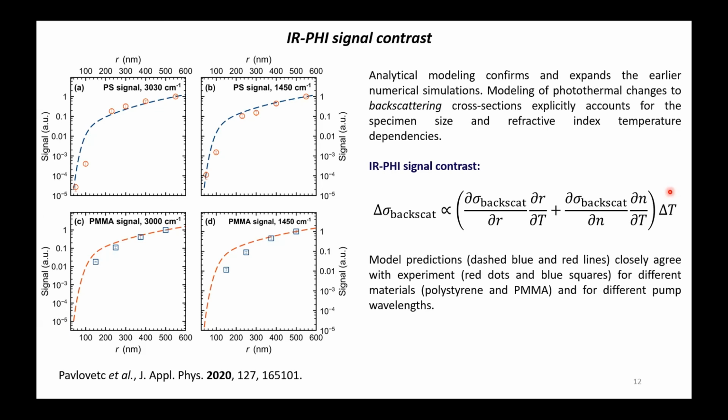Yeah, this is a very nice question. So yes, you can have some spectral wandering of some bonds with temperature, and to vary temperature, it's again going to depend on the particular sample of interest, and its thickness, its size, because we can estimate temperature changes on a back-of-the-envelope basis, and we can vary incident power intensity very accurately, and we can make a calibration curve of signal and estimate what the temperature change is going to be there, and change temperature very accurately.